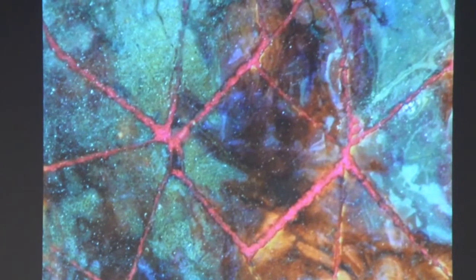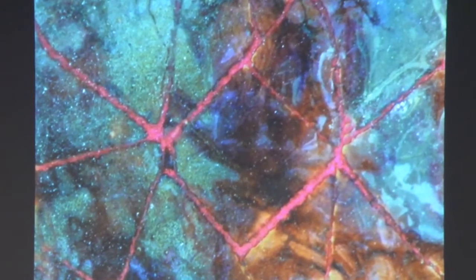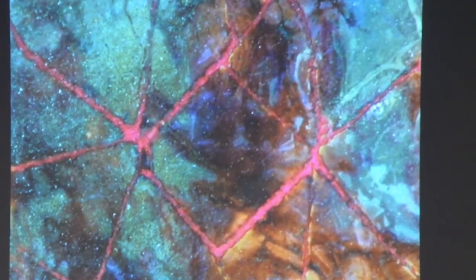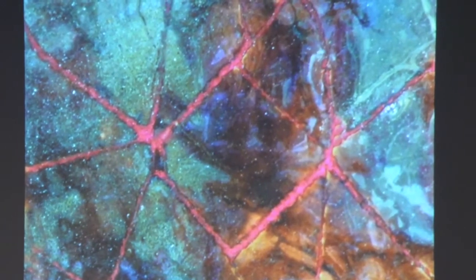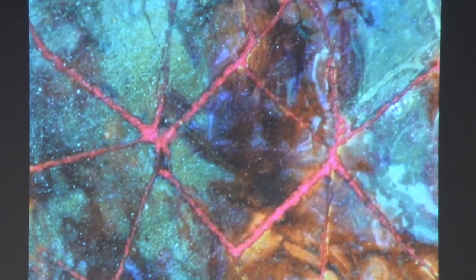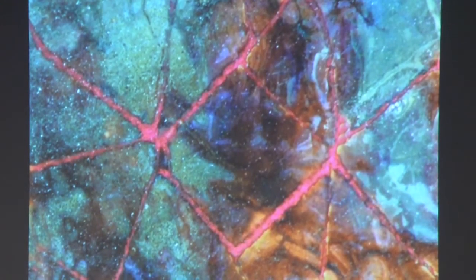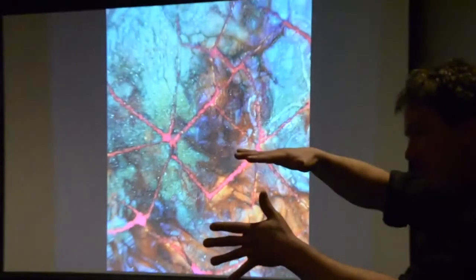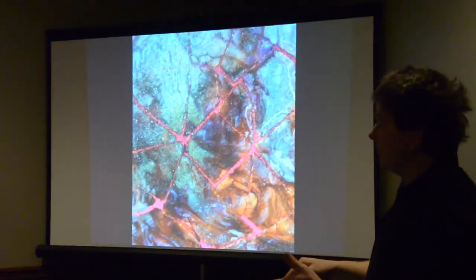It's easy to do quarter-inch thick glass with all kinds of color patterns because when glass sits in the furnace, it always pools up. That's just a function of surface tension versus gravity. Water will pool up maybe 1/8 of an inch thick when you just dump it on the table. No matter whether it's a big pool or a small pool, it's always the same thickness because of that relationship between surface tension and gravity. Glass will be a quarter-inch thick, so if you want it thicker than that, you have to dam it into an area and let it build up. If you want it thinner than that, you've got to roll it out.